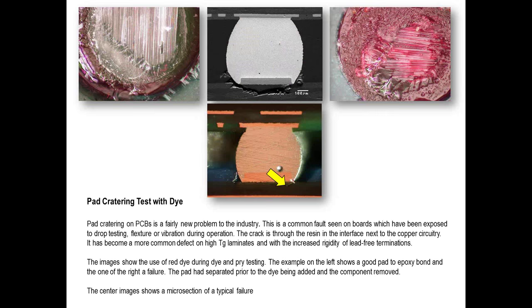Top left is what you would expect to see after dye and pry, where we've ripped the pad off the board, but there is no evidence of the dye present underneath the pad. That was a good interconnection prior to me damaging it. And on the right-hand side, you can see complete coverage of the glass bundles, strands, underneath the pad with the dye. So clearly there was a gap there prior to us doing the testing. Hence it shows up where the fault actually is.